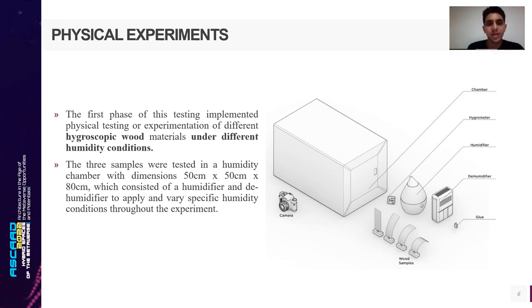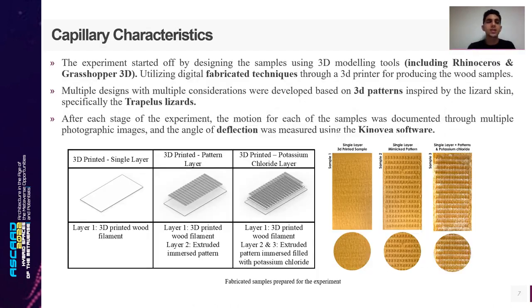The three samples were tested in a humidity chamber, which consisted of a humidifier and a dehumidifier to apply very specific humidity conditions throughout the experiment. The experiment started off by designing the 3D samples using Rhino and Grasshopper 3D, with multiple considerations developed based on the 3D patterns inspired by the lizard skins, and after that utilizing digital fabrication techniques for producing these wood samples using 3D printers.